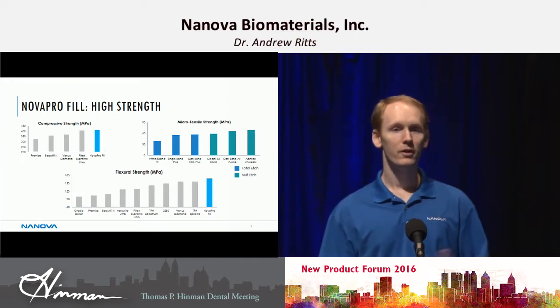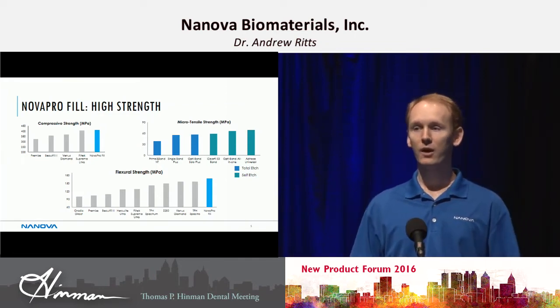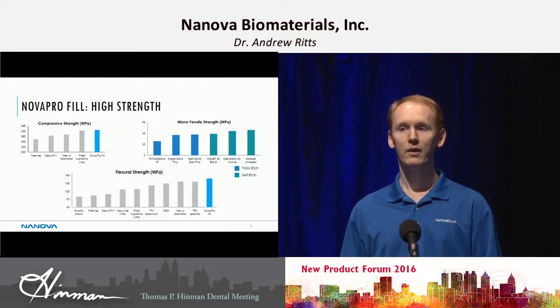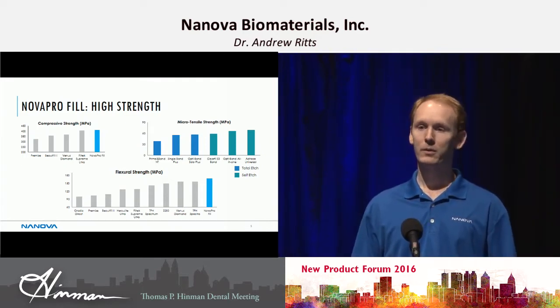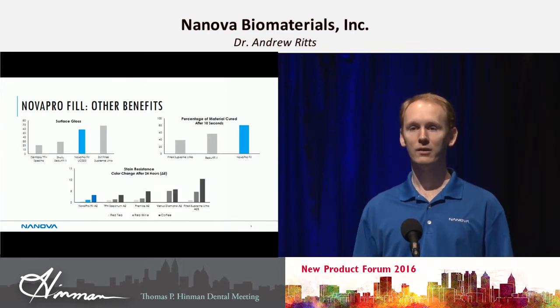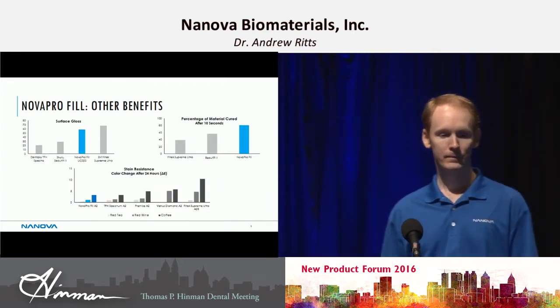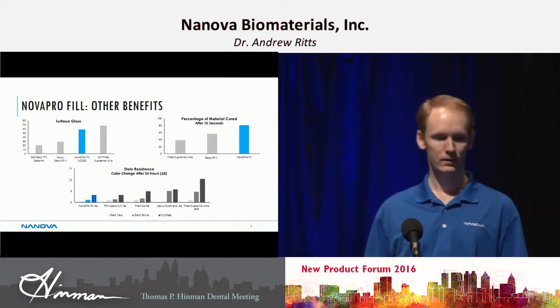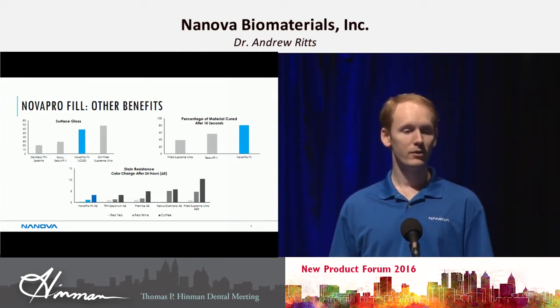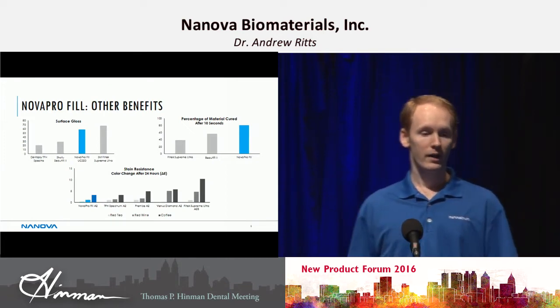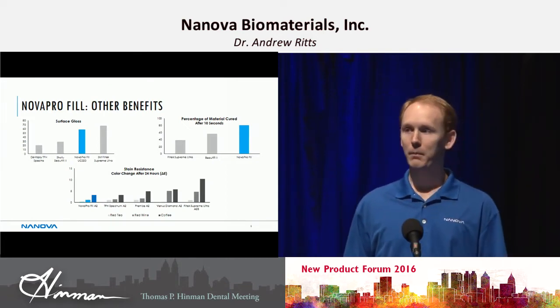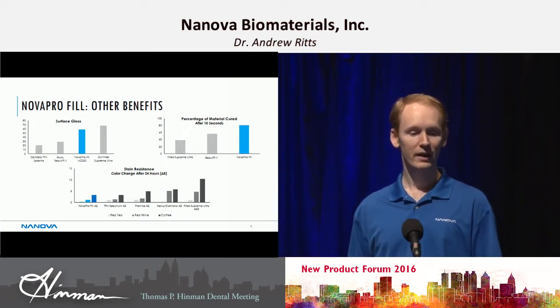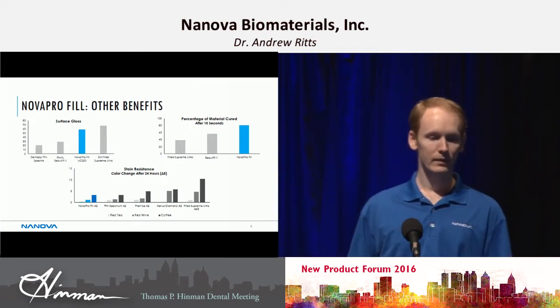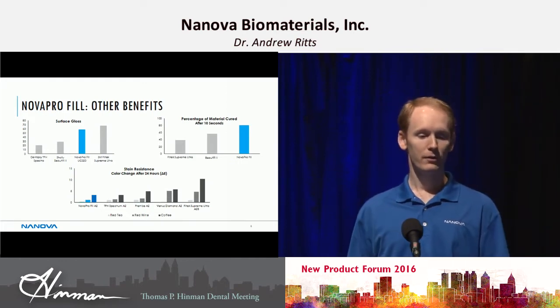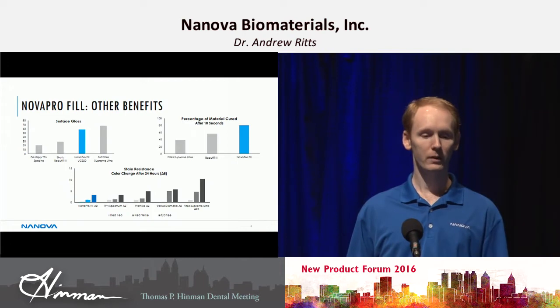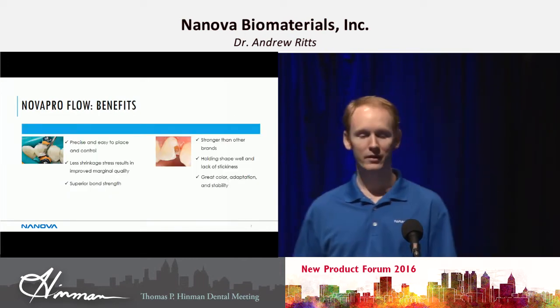And that's what you'll find most other composites aren't able to achieve because they all use particles rather than fibers. With our nanofiber-based composite, we're able to increase the composite strength in ways that make it less likely to fail. Other benefits to NovaPro Fill are there's a high surface gloss, a very high percentage of the material is cured in just 10 seconds, and we have a high stain resistance. As you can see, if you're looking at red tea, red wine, or coffee, we have very low staining properties for our composite.